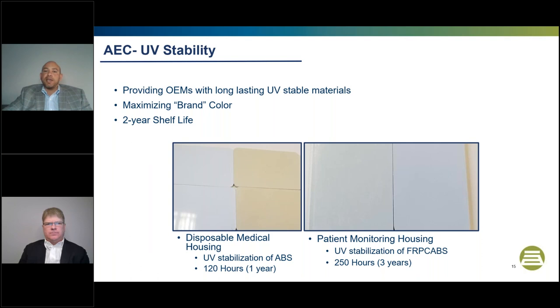This is an FRPC ABS. Our formulation's on the right, current formulation's on the left. This is a 3-year test, 250 hours. We pulled chips every 50 hours and did measurements, and it's a little bit harder to tell, but you can see on the left there was a color shift into the yellow spectrum that showed degradation. And so we showed the OEM that pretty much with no cost increase, if anything, we lowered costs, that we can give you the same color and keep that color for a long time. On the next slide,